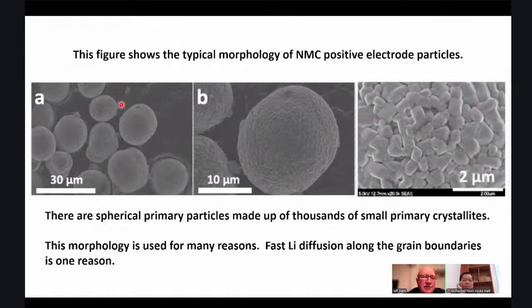And typically, if you look at the positive electrode in a NMC lithium-ion battery, you'll see these sort of spherical particles. And if you look in closer, you'll see that they look to be made up of a lot of smaller subparticles. And when you look really close on a 2-micron scale bar, you can see all these primary particles that are making up this sphere. And they're configured like this for a variety of reasons. And one of them is that the lithium-ion diffusion along the grain boundaries is very fast, so that lithium can get from the electrolyte into the center of the particles very quickly. That means you can charge and discharge your battery rapidly.